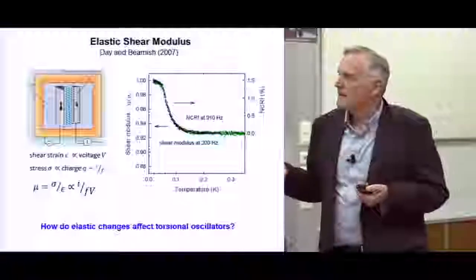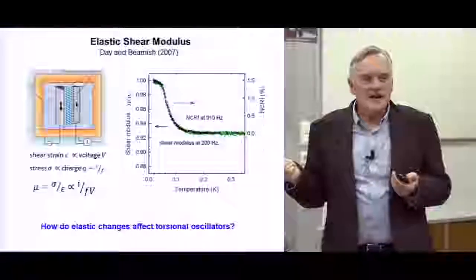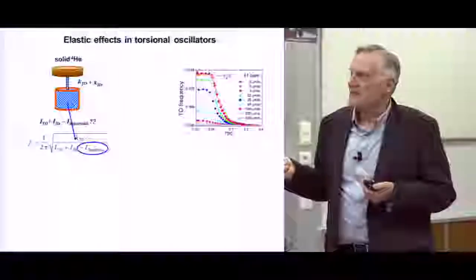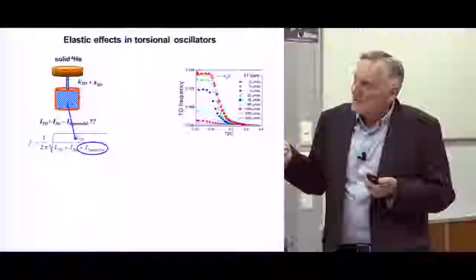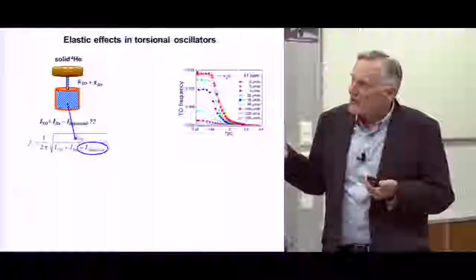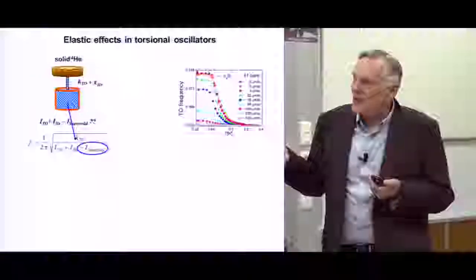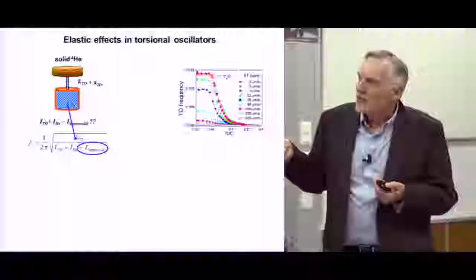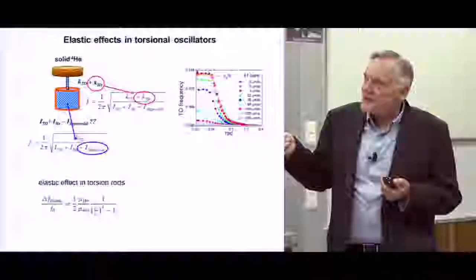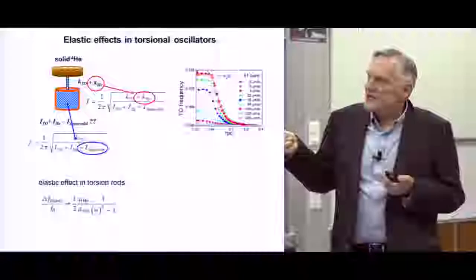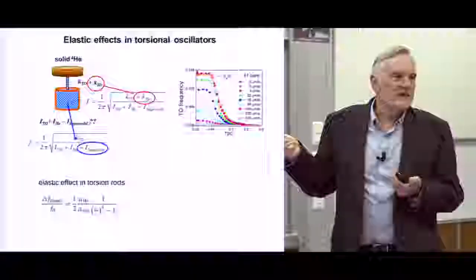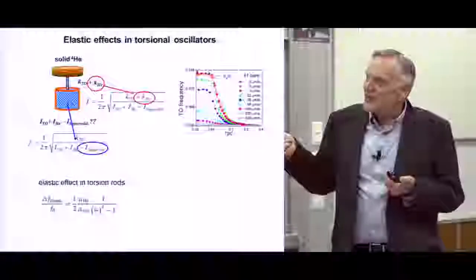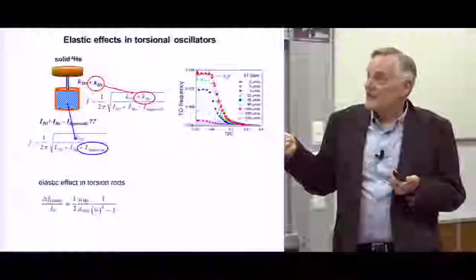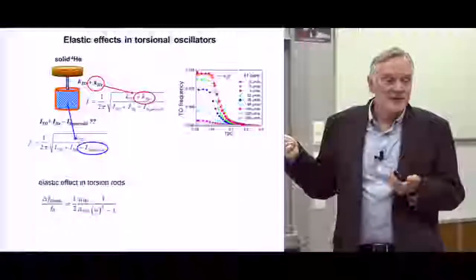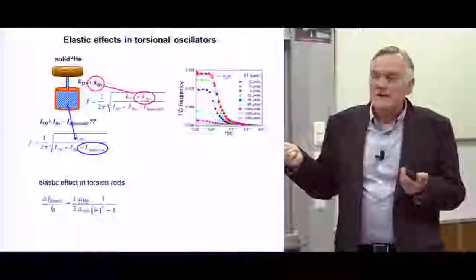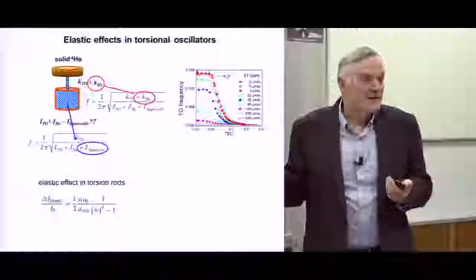So one of the questions this raises: how do these elastic changes, which are real, affect a torsional oscillator? And here's the problem. Here's the experiment with solid helium. Here's the interpretation that this is due to a decrease in the total inertia, which makes the frequency go up. But what you're not paying attention to is up here, this is solid, not liquid. And so solid has its own shear modulus and stiffens the torsion rod. So if you stiffen the torsion rod, that also makes the frequency go up. And we just saw that this change in the helium's stiffness looks just like that. So that was the really big if.